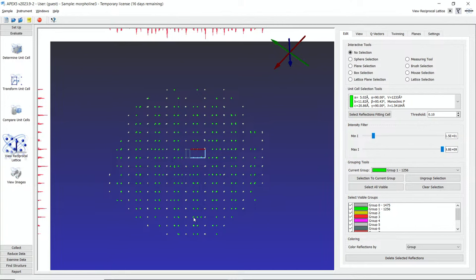And basically what he proposed is to now collapse all the reflections by reducing dimensions. So now we're getting rid of three dimensions, which means that all the reflections that are indexed, the main reflections, will collapse into one position. Okay. And then we have the green ones left over, and you will see what happened to the green